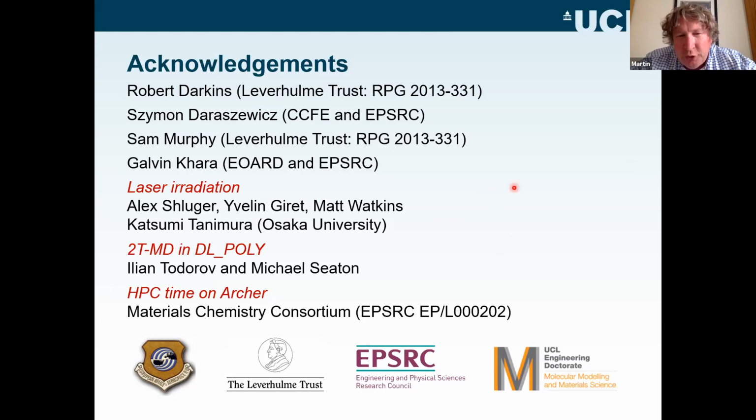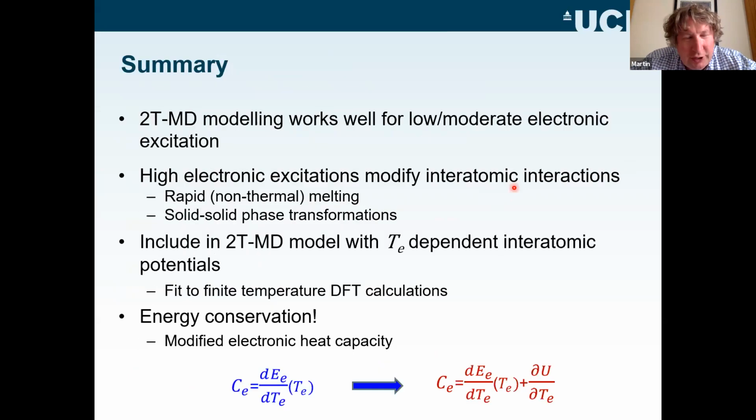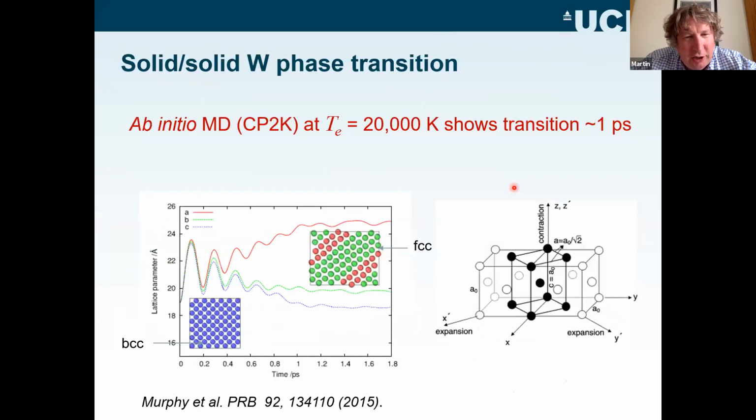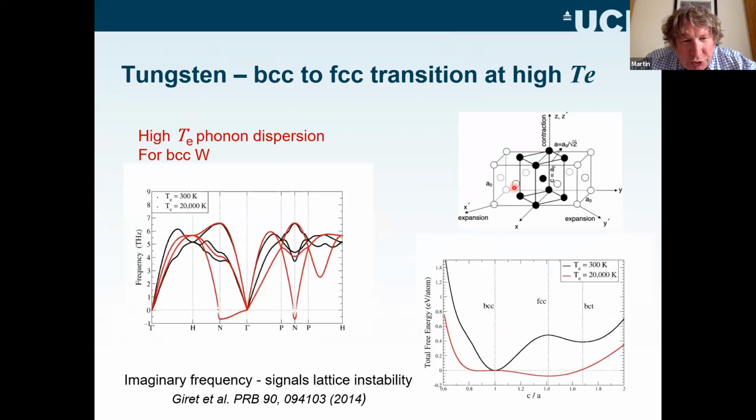But the phonon spectra you showed, I think, the instabilities would not give you a transition between FCC and BCC, because the instabilities are at the zone boundaries. So they will presumably be showing you some other potential instabilities. The FCC to BCC or vice versa essentially preserve the size of the primitive unit cell. So in the phonon spectra, if such a transition were to show up in phonons, that would be in the acoustic modes at the gamma point. So I think what you're seeing in the phonon spectra is some other possible instabilities. Not that they may actually exist, because your FCC, BCC are quite likely, I think, to still dominate.